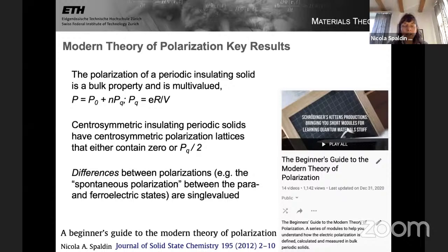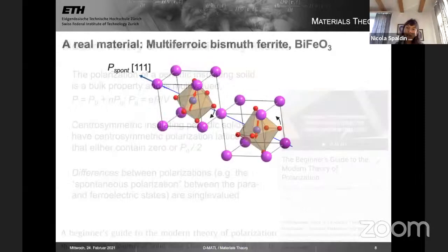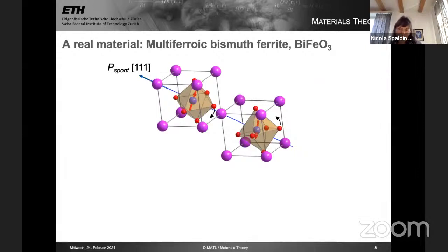Now I want to apply it to some real materials. The material that I'm going to discuss today, just one particular polarization in one specific material, is a perovskite structure oxide, bismuth ferrite, bismuth iron oxide. Bismuth ferrite is multiferroic, so it has the combined property of being ferroelectric. It has a spontaneous ferroelectric polarization, a spontaneous electric dipole, and it's also magnetic. It's actually antiferromagnetic. Its crystal structure is the perovskite structure, so it has an iron ion at the center of an octahedron of oxygens.